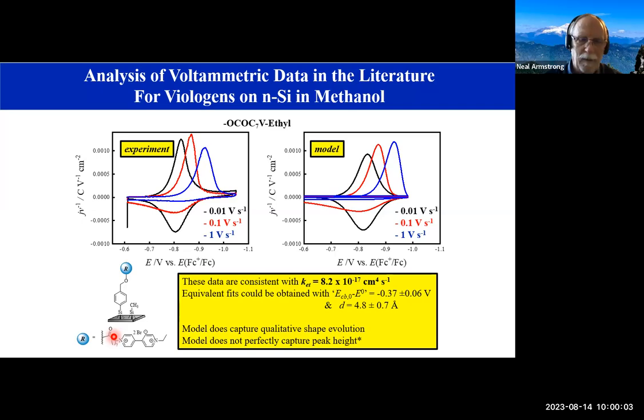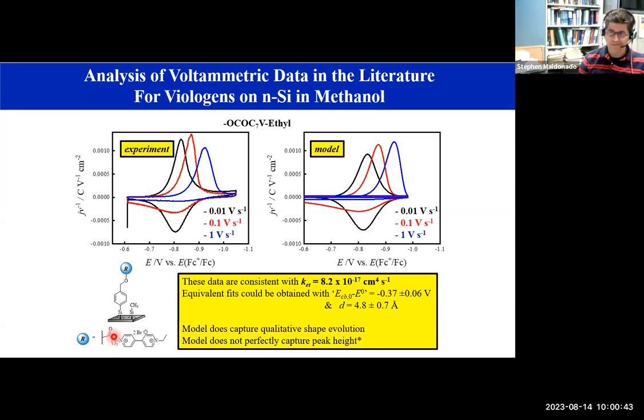I'll go look for the paper, but there's a kind of brilliant paper that slipped beneath the radar that Akira Fujishima published on boron-doped diamond years ago, where he varied the doping level in that system and was able to see pretty pronounced changes in electron transfer rates just due to the heterogeneity of the distribution of the dopant. I don't know whether anybody really picked up on that beyond that point, but I'll go looking for it. It might give you some clues. Otherwise, this is fantastic stuff. Thanks, Neil. I appreciate it.